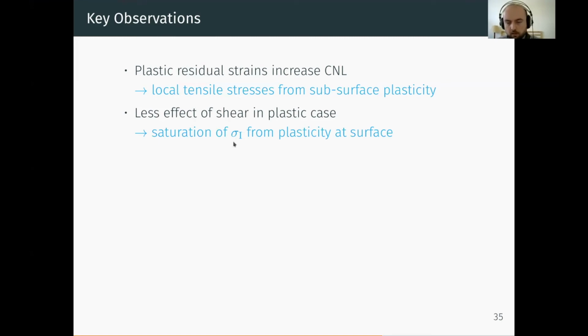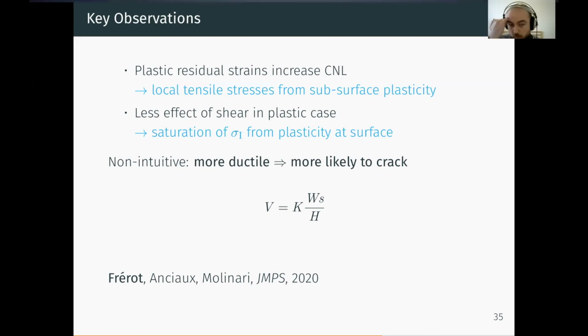And again, we see the saturation effect of sigma 1 due to plasticity, and this is why we don't see as much of an effect when we have shear stresses. So what I want you to take away from this is that a more ductile material, a softer material, is more likely to crack due to subsurface plasticity. This isn't something that's been directly observed in experiments, but this is something we expect from Archard's wear law. We expect to have more wear volume as we decrease the hardness, as we get softer and softer materials.